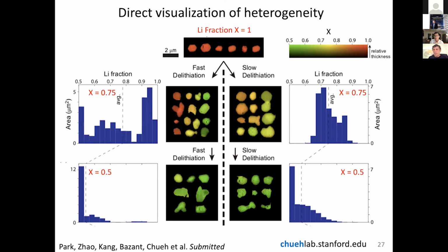But if you do it very quickly, this is where we saw phase separation, you actually see a very different behavior. So rather than having a single peak in the histogram, which means very uniform composition with some broadening, you actually see a bimodal distribution, which means that you now have lithium-rich and lithium-poor particles, and graphically you can see this. So this tells us that diffusion isn't the explanation, because if diffusion was the explanation, then you would see a uniform, single-modal distribution for both cases.